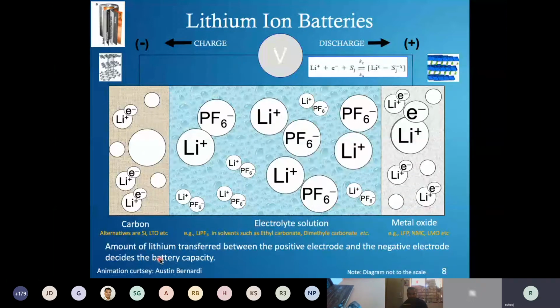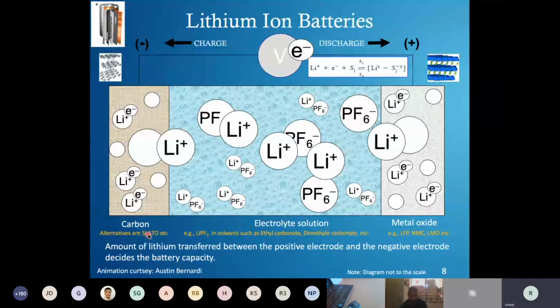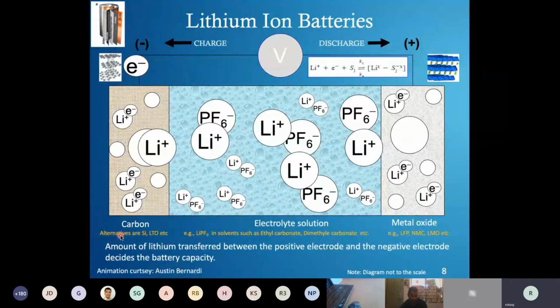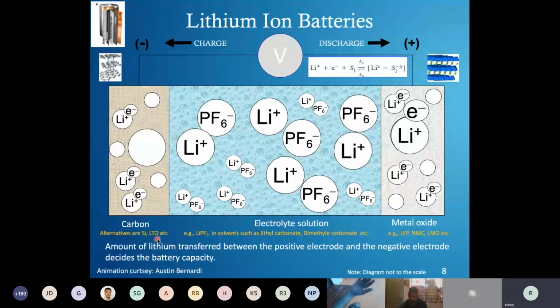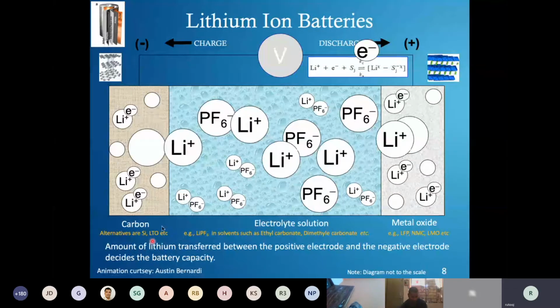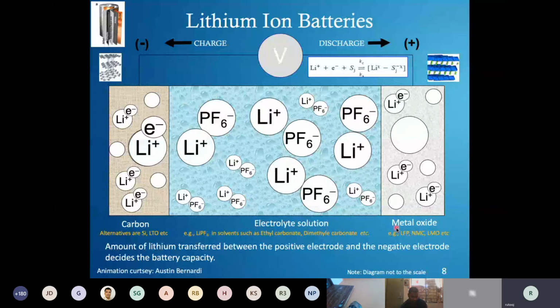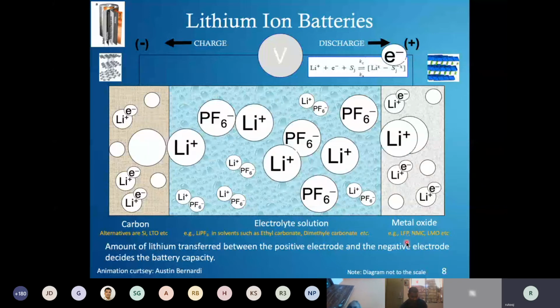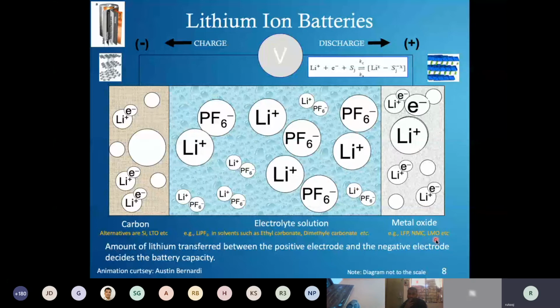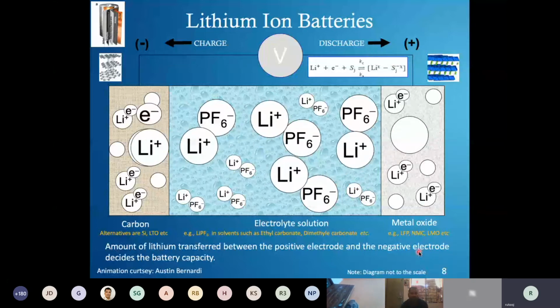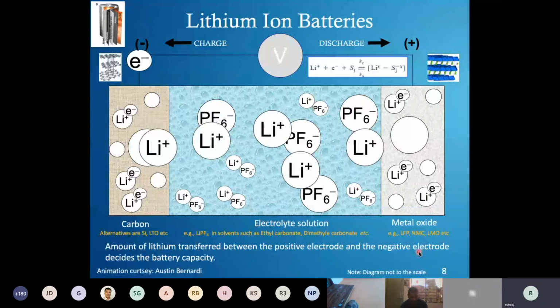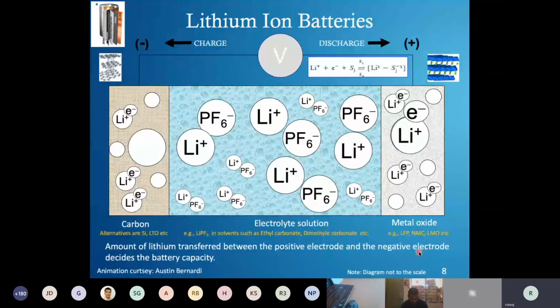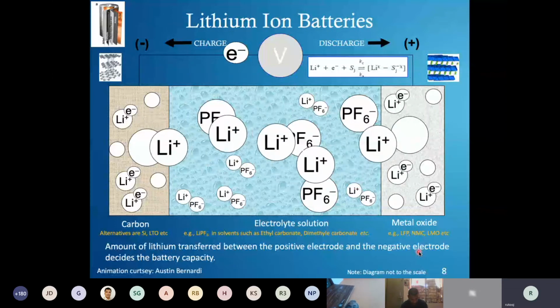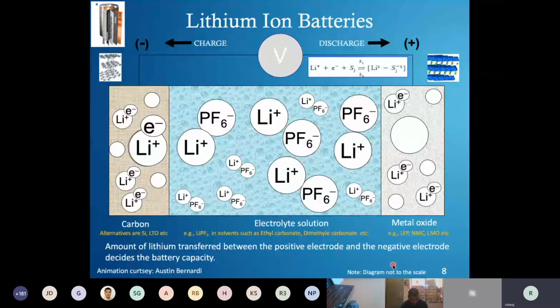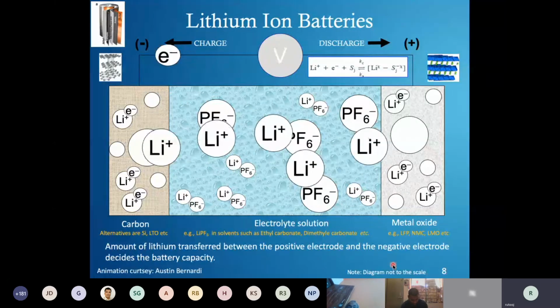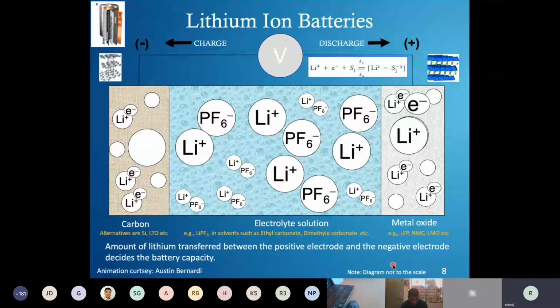Typically, the negative electrodes are graphite based, either natural graphite or artificial graphite. The alternatives are silicon or LTO, lithium titanate, in certain cases. Typically the positive electrodes are LFP, lithium iron phosphate, NMC, or LMO, etc. Lithium iron phosphate or NMC, all of these are lithium-ion batteries because ions are the carrier of current in the electrolyte. So I see a lot of people saying LFP is different than NMC, but all of them are lithium-ion batteries at the fundamentals.